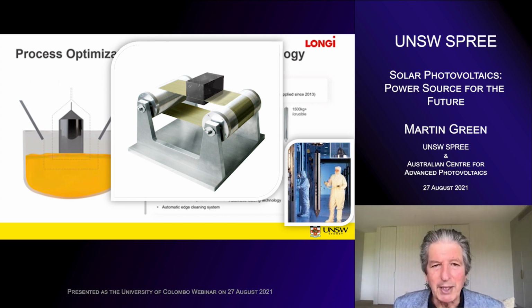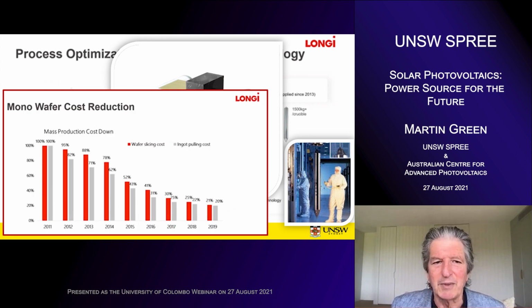And you grow these big cylinders of material. You then slice the sides of those cylinders to get a squarish type cross-section to the cylindrical shape. And then you slice that sort of loaf of bread, not into slices of bread, but into silicon wafers by this sort of machine that's shown underneath me there. So the wires are guided up through the material, and they're impregnated with the diamond, so they cut the silicon away and make these very, very thin wafers. So the wafers are about 1/6 of a millimetre thick these days, so, much less than a millimetre in thickness. So very thin wafers. And down the bottom right, you can see one of these big crystals grown. So all perfectly arranged silicon within that material.